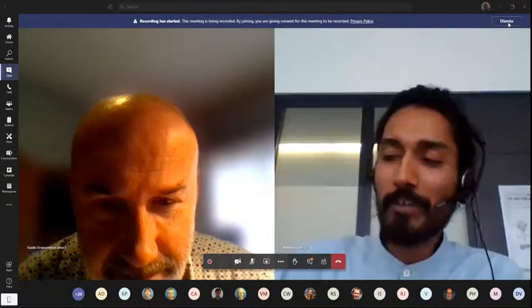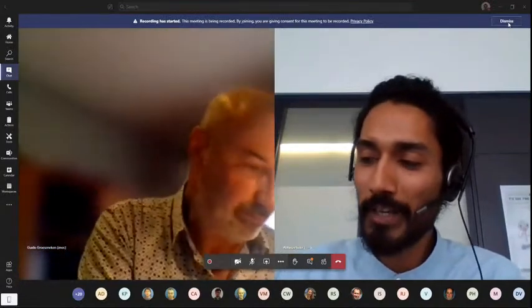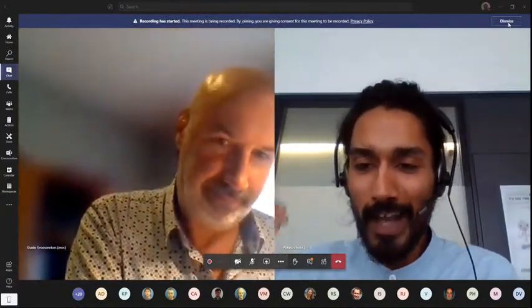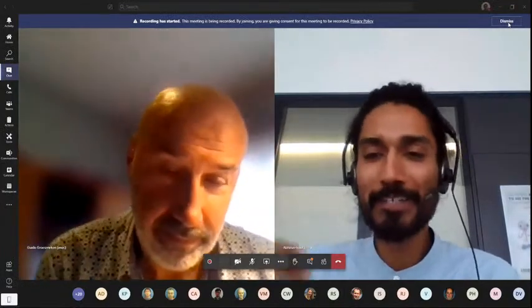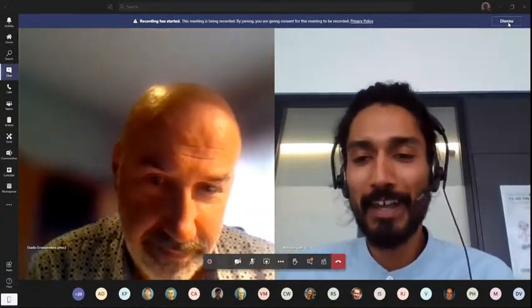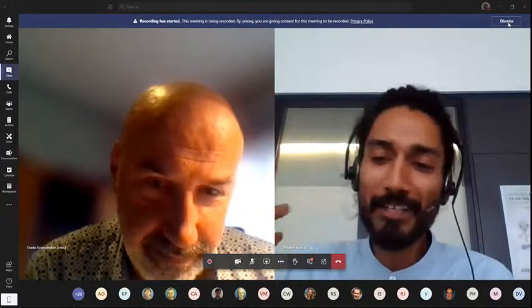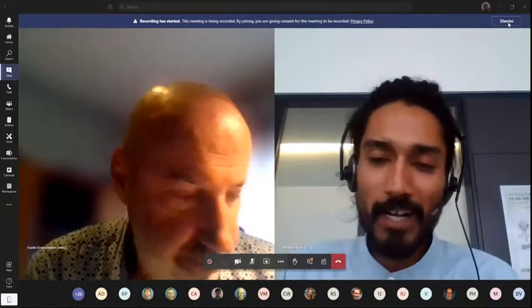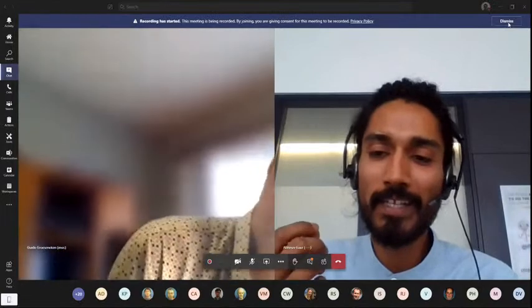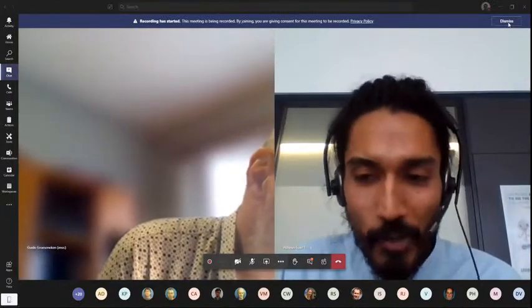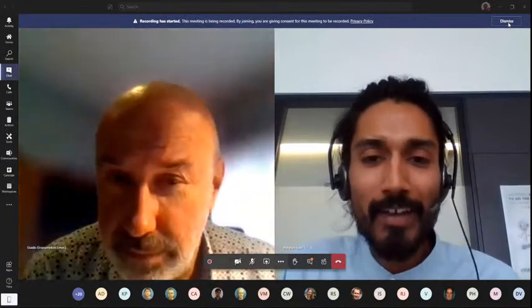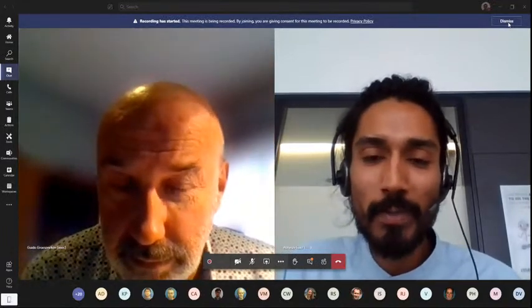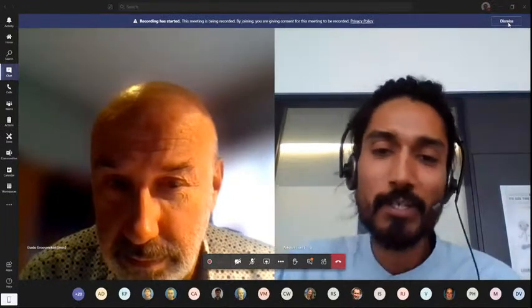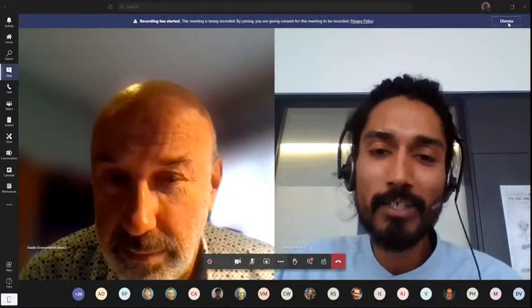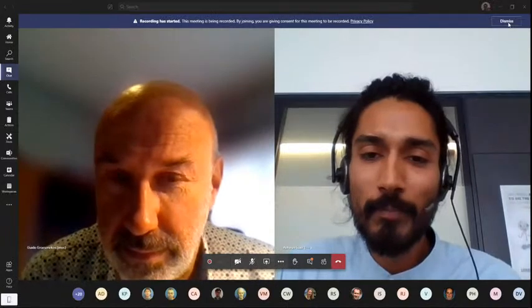Actually, if you look at this, if oxide thickness was really playing a role, then it should be more consistent. As we reduce the thickness, either mobility increases or mobility consistently decreases. But we see a dip over here, and it's only 3 data points. So it's very difficult to say that it's an oxide-based effect. It could also be that the transfer was slightly off in the 4 nanometer or 12 nanometer case, or there was some sort of interface residue present in these oxides or in these devices, which led to this.